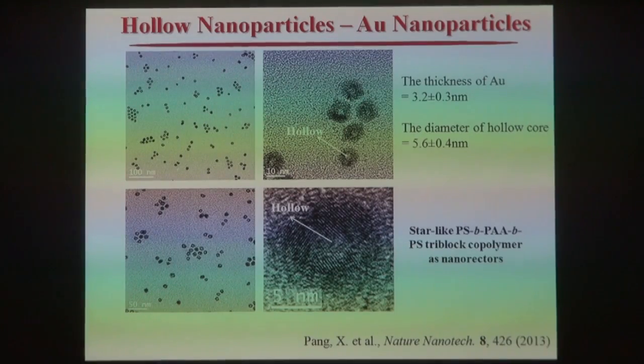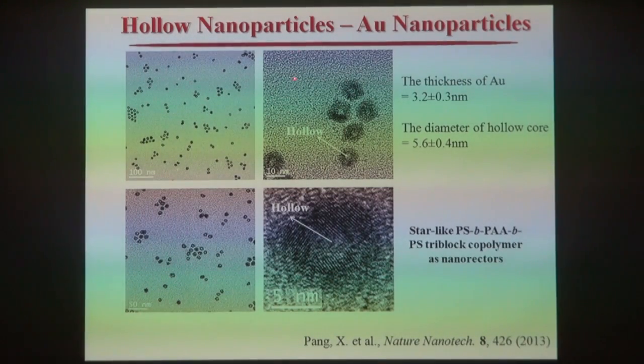So here's one example. Here we have hollow gold nanoparticles. Here you can see in this low resolution TEM image, the center of the particle actually appeared bright, indicating it is hollow. Here you can see a high resolution TEM image. Here you can see the crystal lattice, indicating it is a polycrystalline gold nanoparticle. The thickness of the gold is about 3.2 nanometers, and the diameter of the hollow core is about 5.6 nanometers.